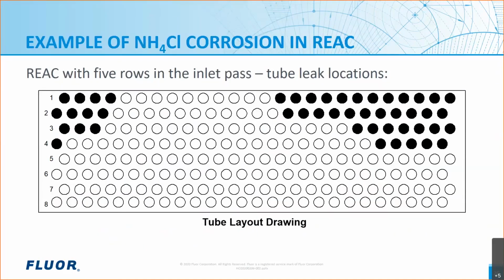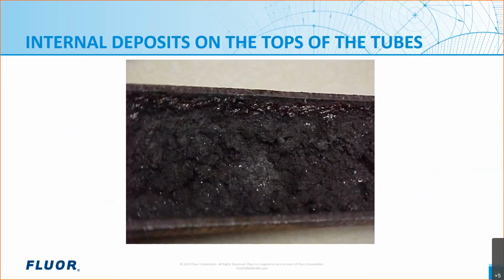So the inlet nozzle is at about the center of the bundle, and you can see that the worst leaks are in the far upper corners where the water would have a very tough time reaching those corners. So the water by gravity just goes to that bottom row in the inlet pass. So here's one of the tubes with a leak. The tube was removed, and now it's been sectioned right through the 3 and 9 o'clock positions, and we're looking right at the top of the internal surface of the tube.